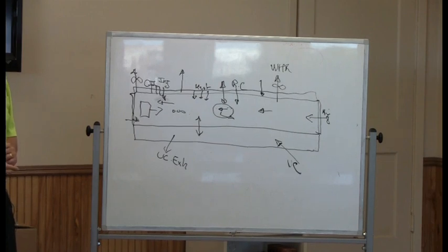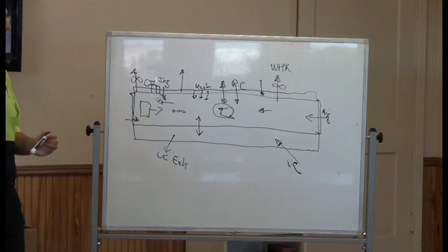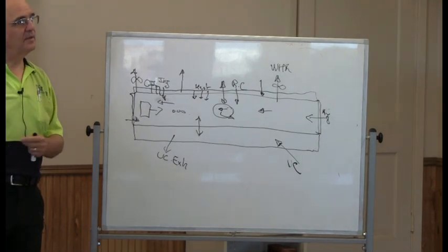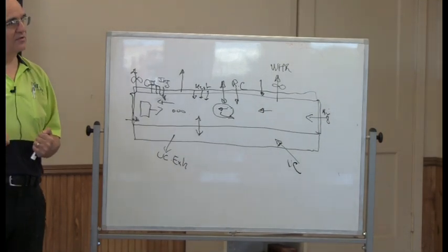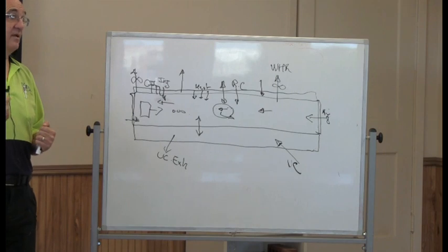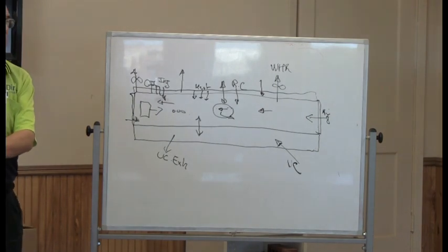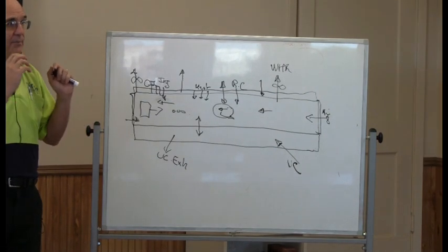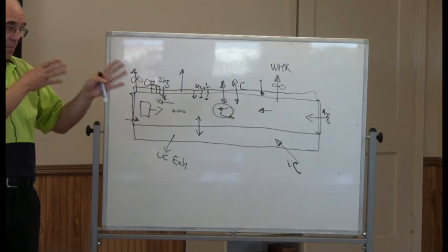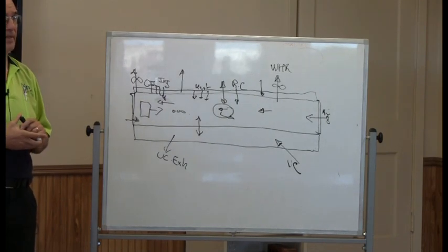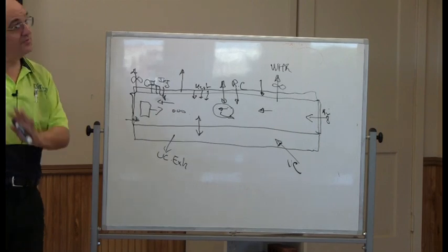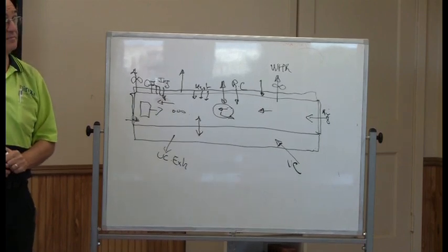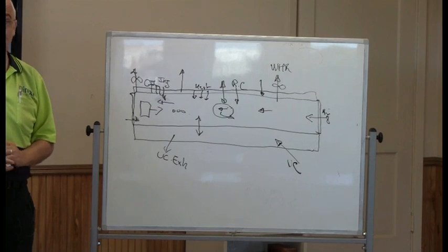Okay? So definitively, if you have a booster, a makeup burner, and sometimes you feel like maybe we are demanding too much on the kiln, that's when you should say, leave the kiln alone, bring some fresh air, open up your booster burner, and bring the volume, bring the heat where it's needed, when it's needed, and leave the kiln alone. If the kiln is properly running, don't disturb the kiln. Okay?